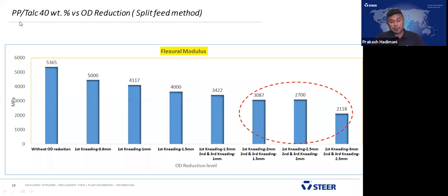Okay, in the same application, PP talc 40 weight percent, with no OD reduction, the flexural modulus is maintained. It is constant, and up to the first kneading, not much changes. After the first kneading we start finding a difference. When you do the 1.5 OD reduction, there is a slight reduction in the stiffness.